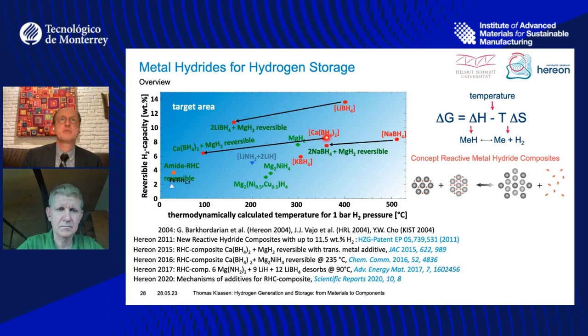And this concept has been proven also for others, like here for potassium and for sodium. And the most recent is actually here. That's a reactive hydride composite involving amides, lithium and magnesium amides. And this gives you a thermodynamic temperature of 30 degrees C, comparable to iron titanium. However, the problem is now you have a reaction of metallic atoms with each other. Diffusion is much more difficult. So while thermodynamically it's perfect, kinetically it doesn't start before 95 degrees C.